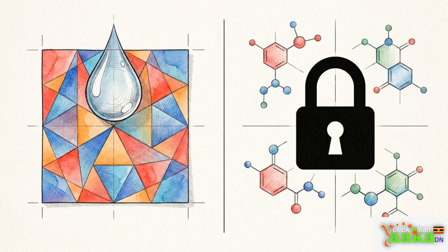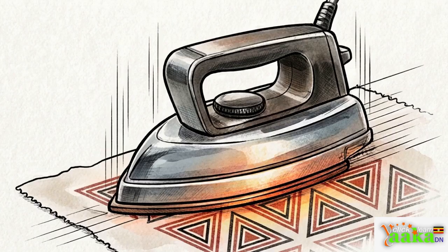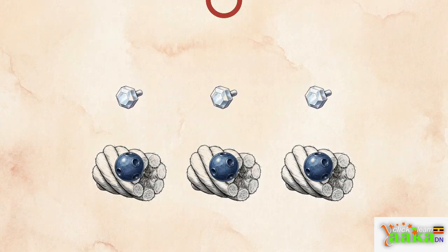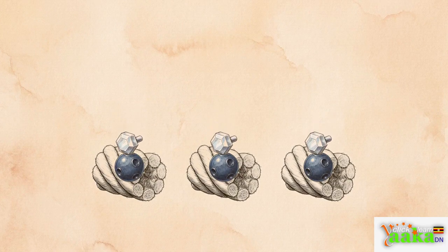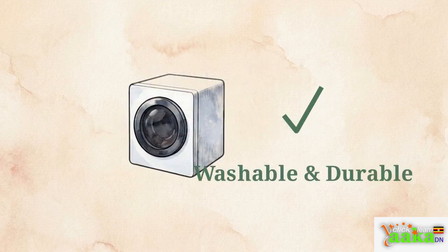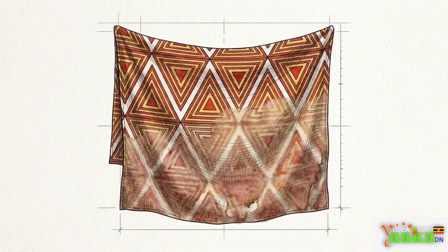Water-based fabric paints require a chemical stabilization process known as the final fix to become permanent. For most garments, the catalyst for this chemical bond is extreme dry temperature, achieved through heat setting. Holding a dry iron over the printed motif for 3 to 5 minutes triggers a reaction. The heat bakes the pigment polymers, cross-linking them directly into the molecular structure of the cotton fibers. Finally, the fabric must undergo a mandatory curing time. The chemical bond needs a full 72 hours to fully cure and stabilize before the fabric can safely touch water. Without executing the proper heat setting and curing chemistry, all previous additive and subtractive design work is strictly temporary.